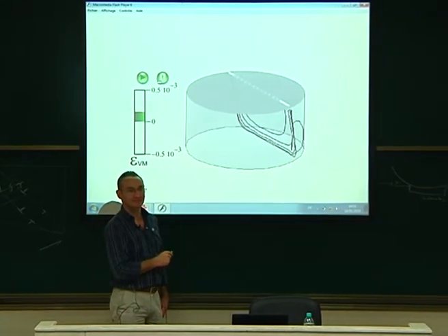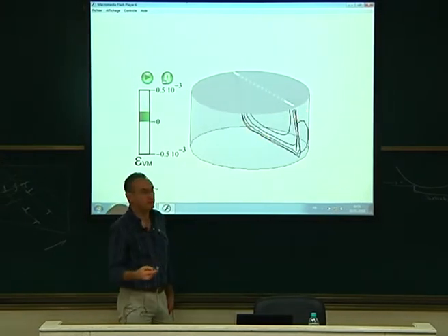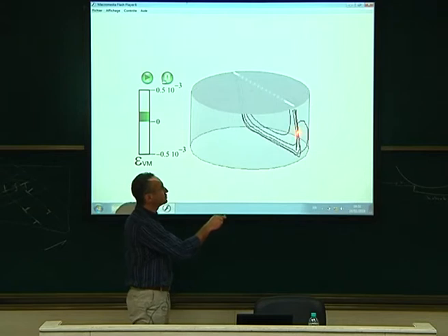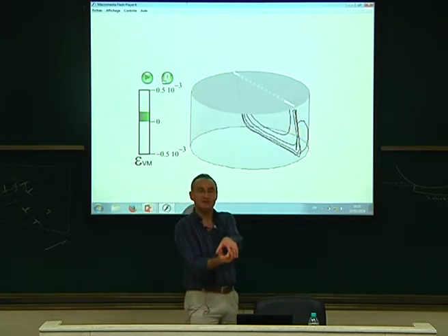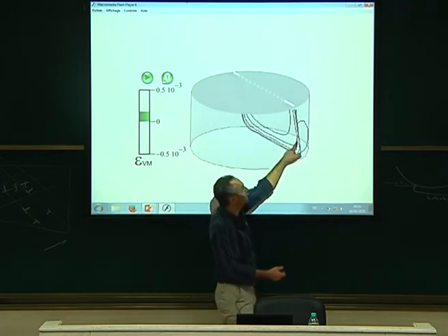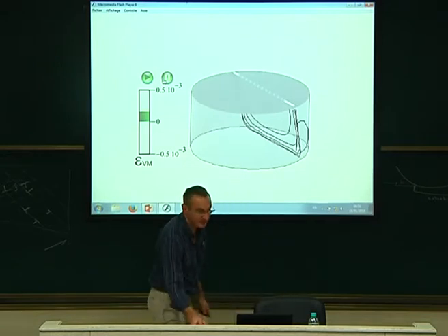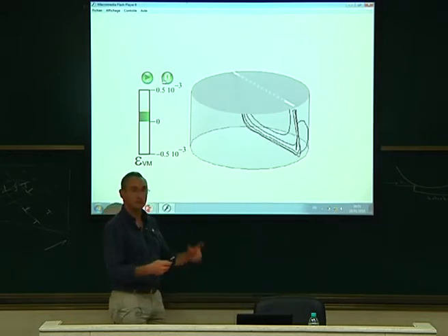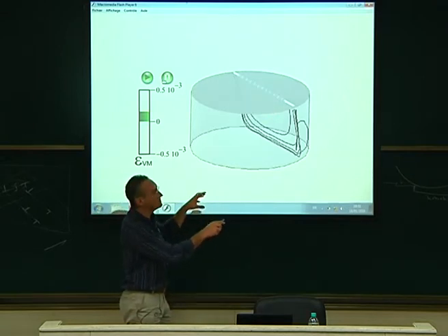Cross-slip. They cross-slip, very easily, when you have the pileup. Edge cannot do anything, but the screw dislocations can cross-slip. Like I explained last time with your wet hand and the soap, because of the pileup you are pressing on the dislocations, and very soon one will go out. So this is what happens here. Because of cross-slip, although you start with a single dislocation here, you will very quickly have dislocations everywhere.